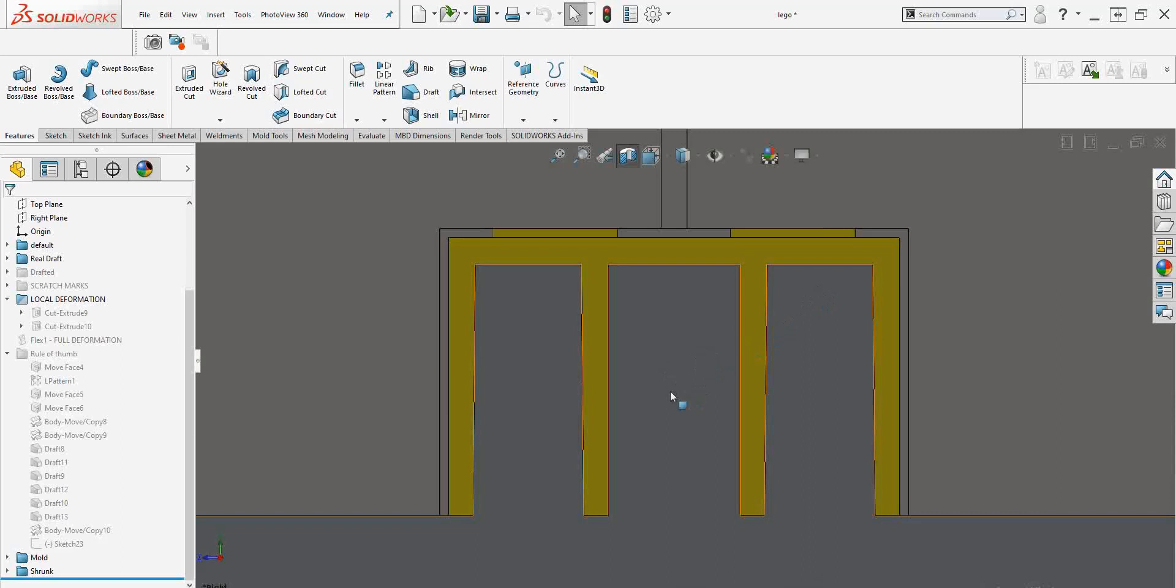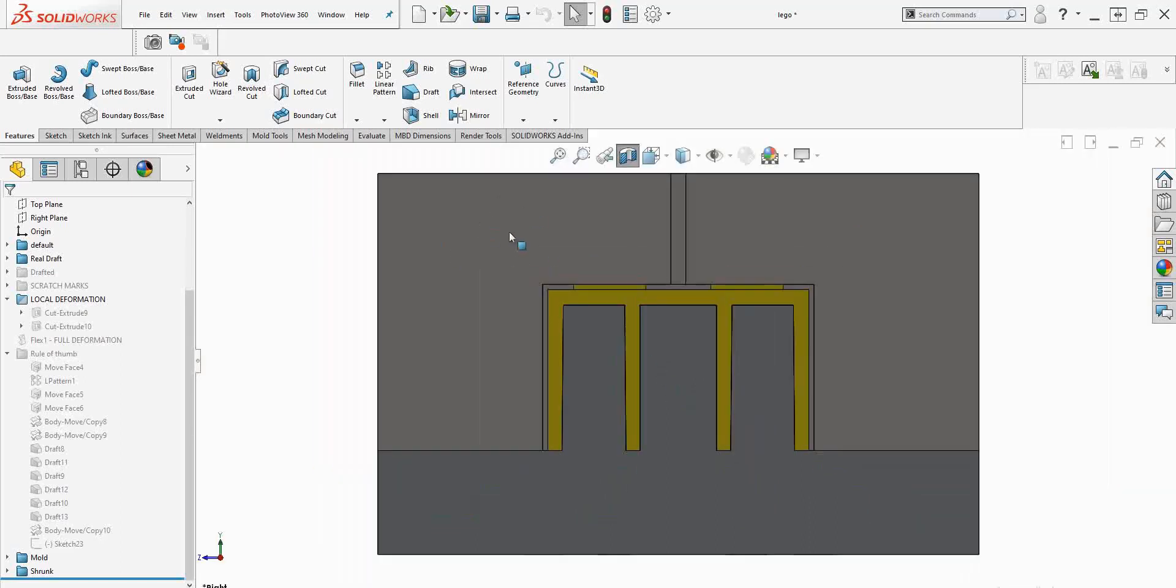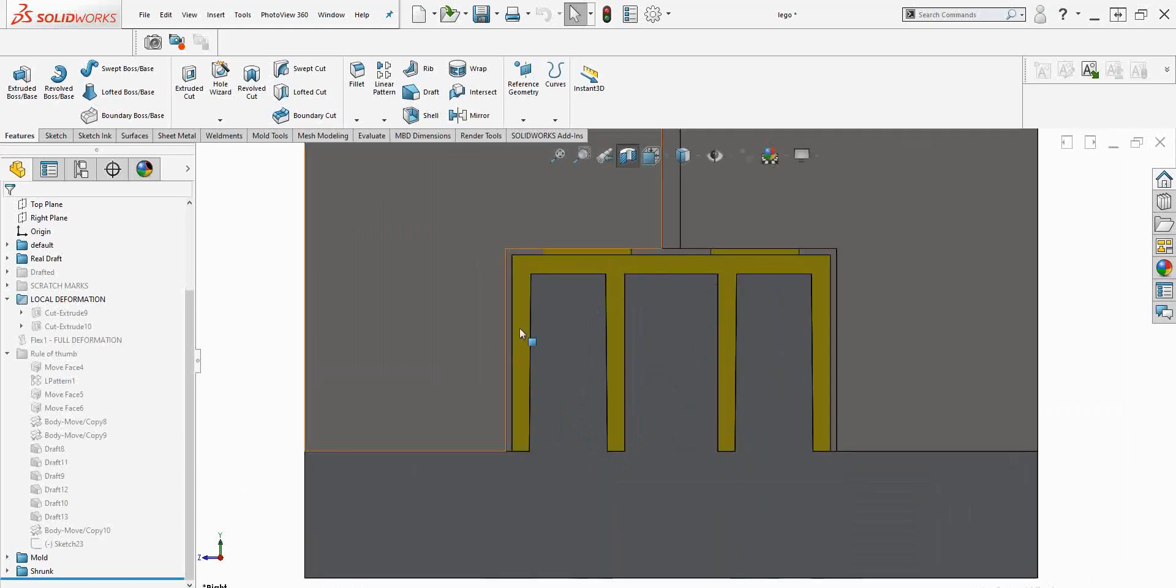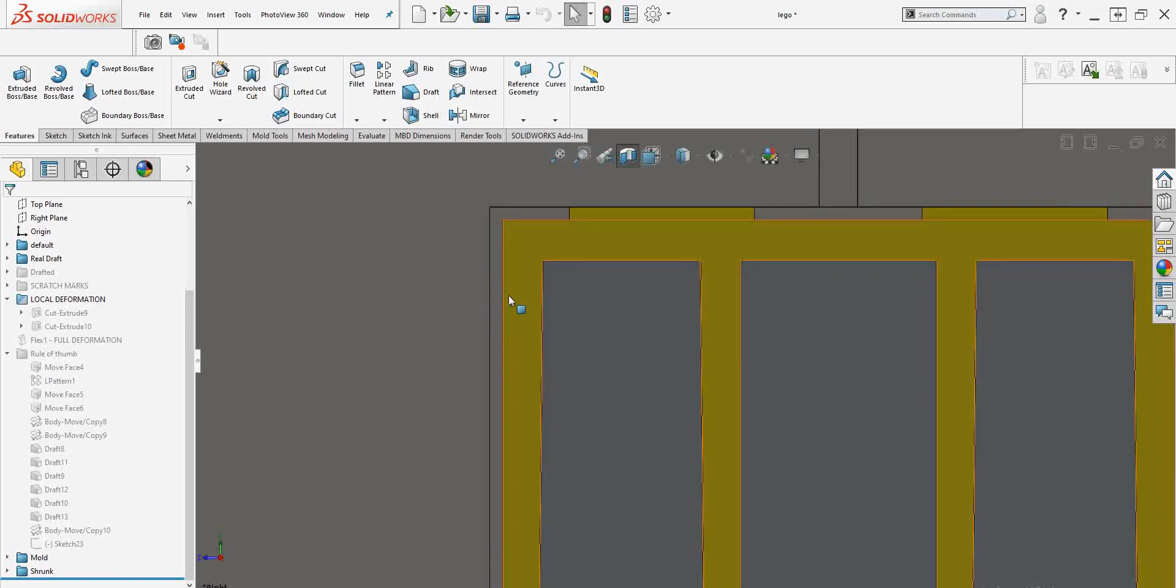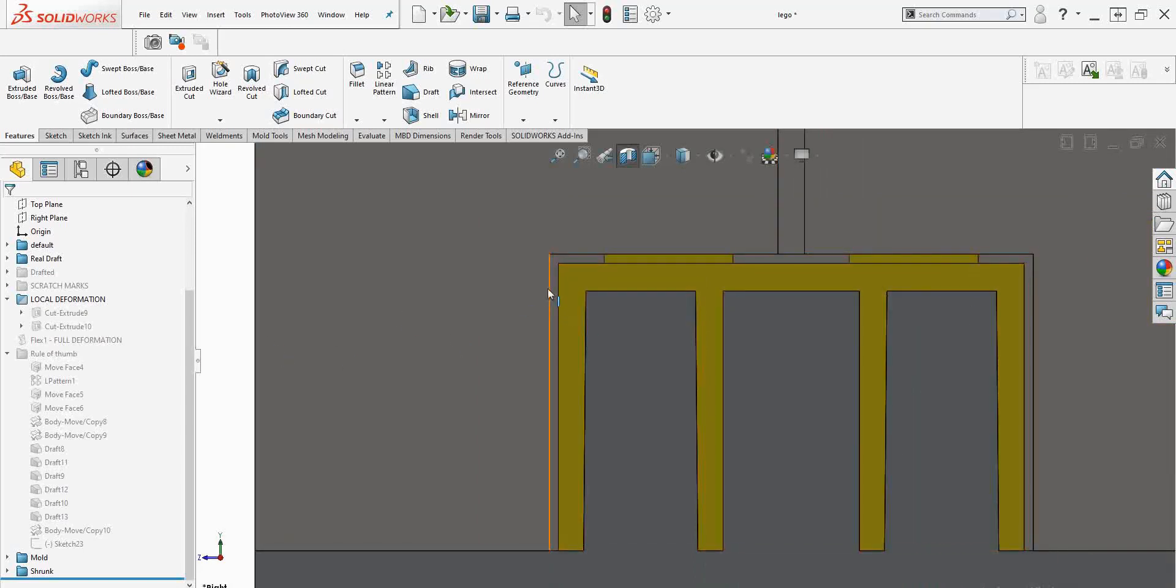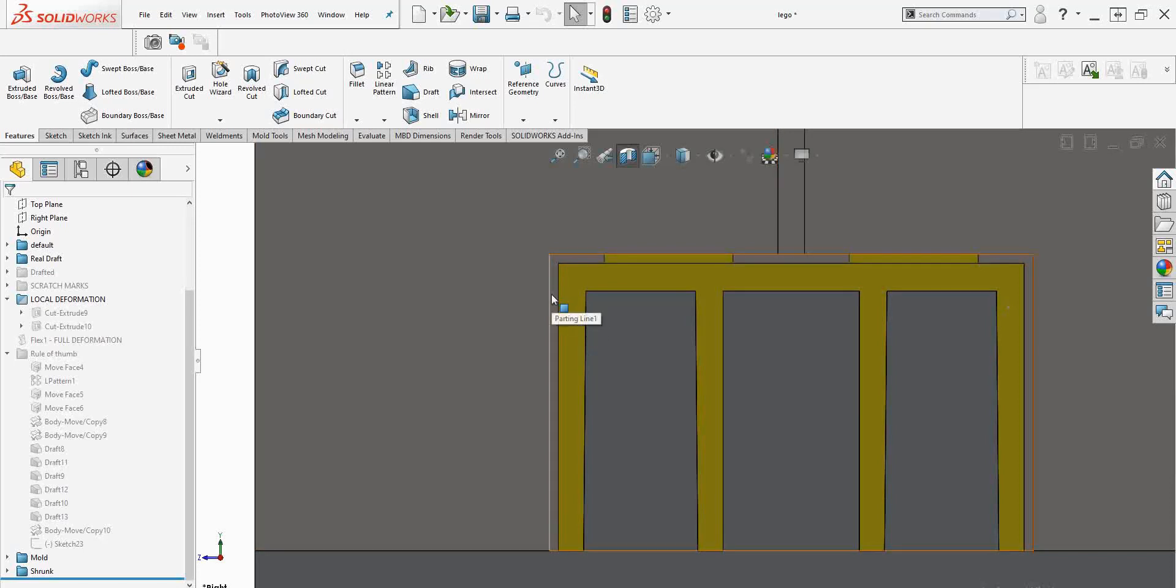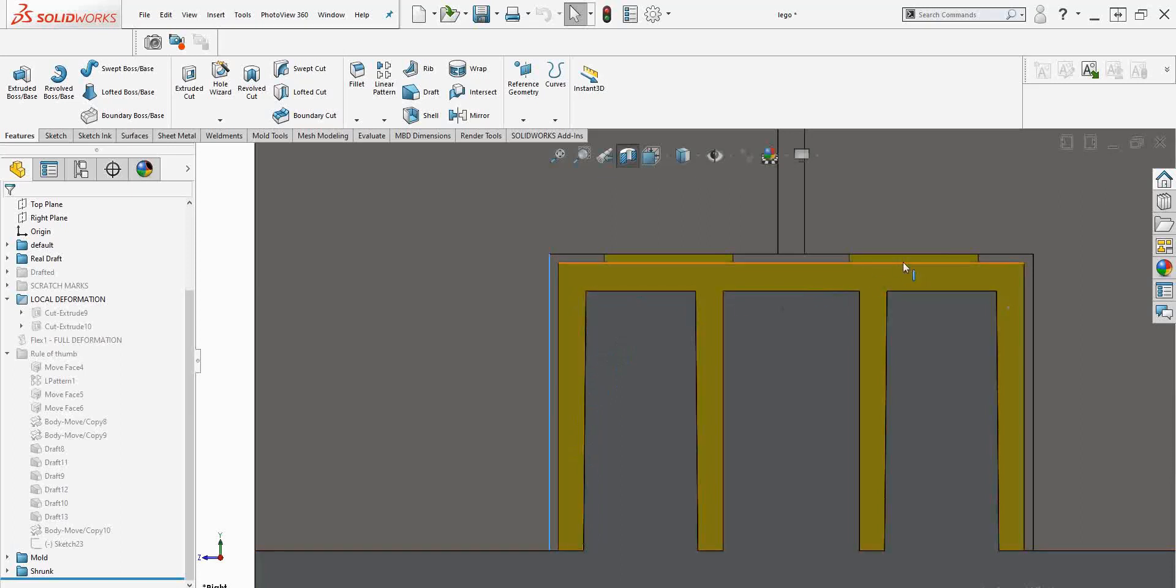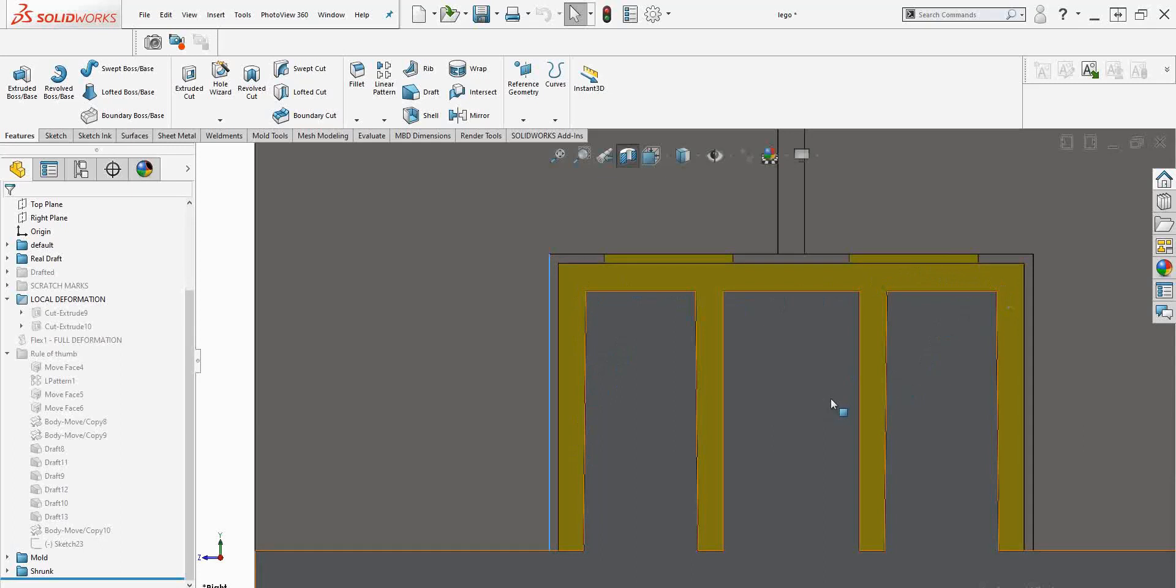So it shrinks inwards. So it doesn't shrink towards this cavity block, this block on the top. It shrinks towards the core block. Core block's at the bottom here. So it actually separates. The walls actually separate a tiny bit. This is exaggerated for the purpose of this video. But in real life this gap might be something as small as 0.1 millimetre. But the point is that does relieve friction between the part surface and the mould surface here. It is making it easier to eject from the mould with concerns with these outside walls. But these inside walls have a far more intimate contact with the plastic as it's shrunken in the direction of the core block and onto it.